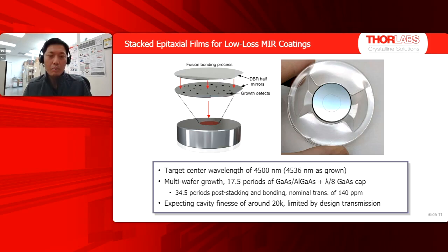And schematically, you can think about taking a single wafer, which could be 6 inches. It's much larger than the coating size that we need. You can take that much larger wafer, fold it on itself, making it double thick, and actually achieve your design number of layers by doubling up on the wafer. And so that's shown schematically here with 2 DBR half mirrors that are bonded to themselves, and that whole assembly then bonded onto the optical substrate. So that's a pretty harebrained idea.